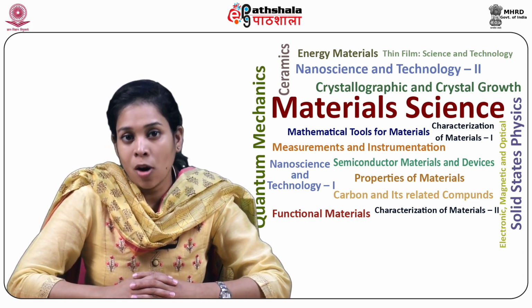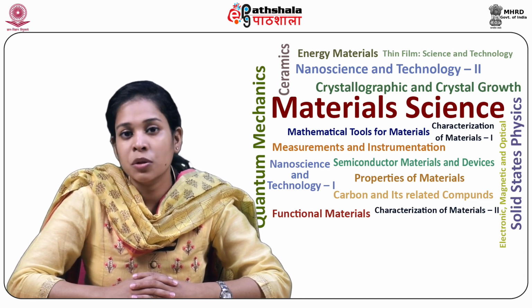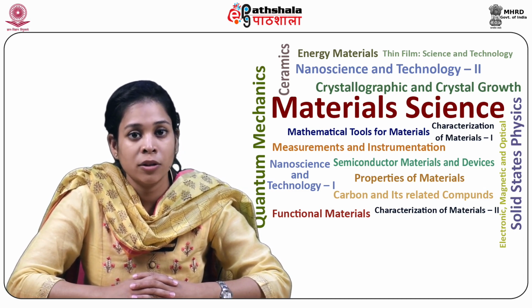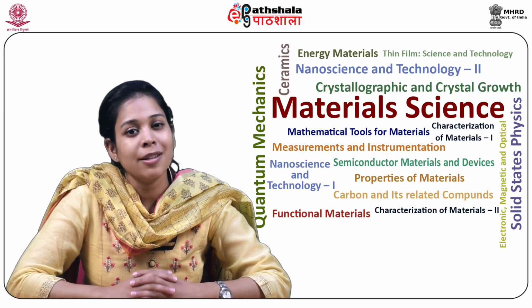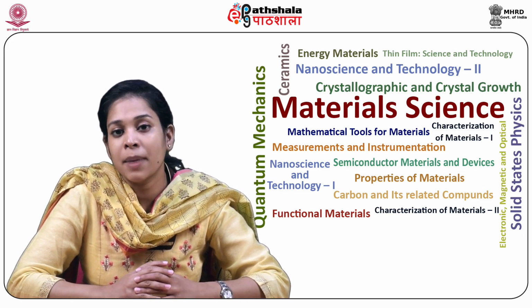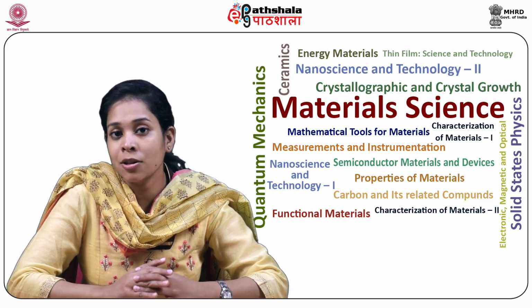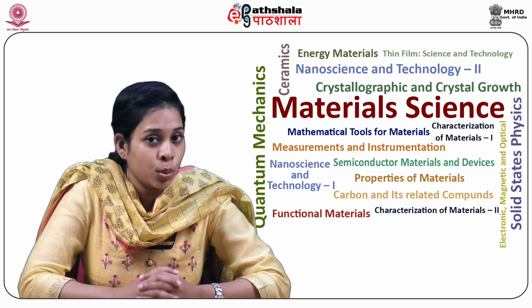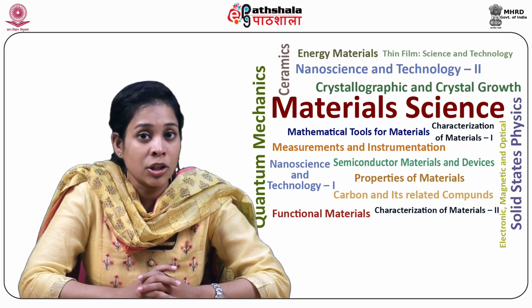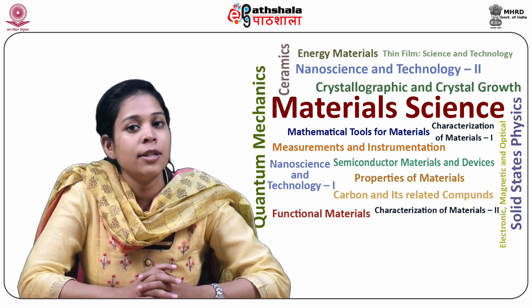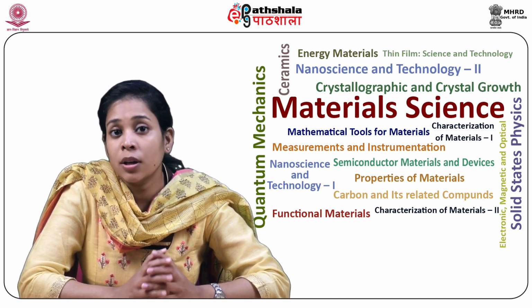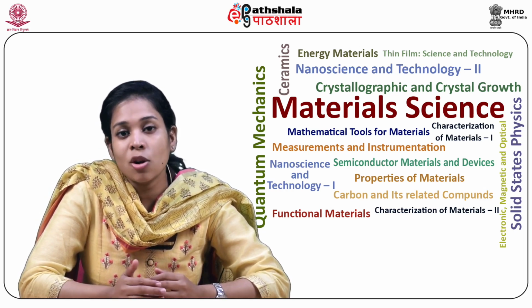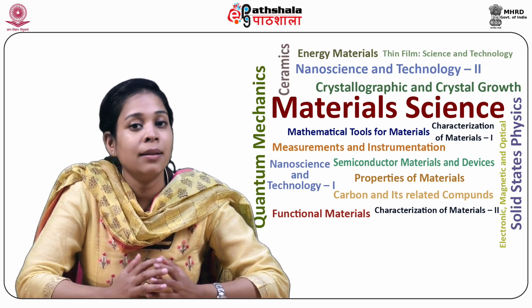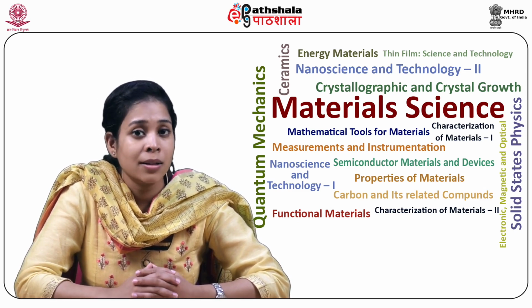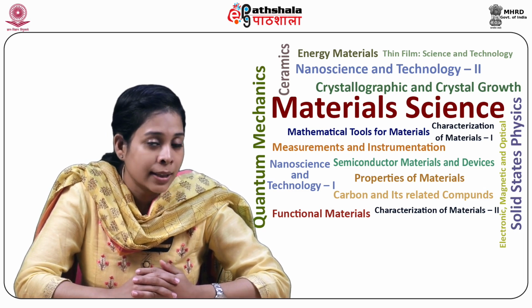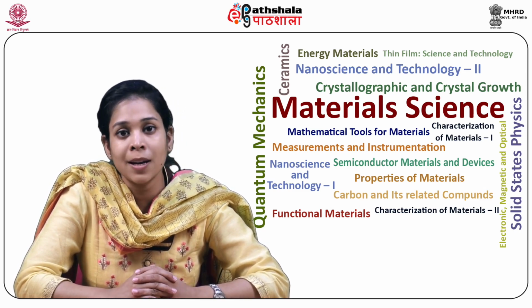Then we moved on to the ionic solids which follow Pauling's rules for structure formation, which are essentially based on minimization of electrostatic energy. In Pauling's rules, we discussed the condition on the ratio of the radius of cations and anions, Rc divided by Ra, where Rc was the radius of cation and Ra was the radius of anion.